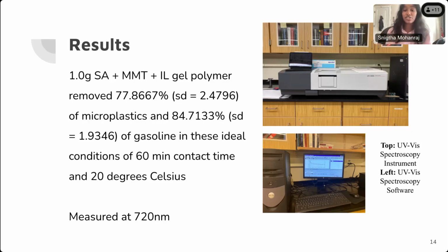And then there was this characteristic peak in a lot of the samples around 720 nanometers. And like I said, I've been working in water contamination for a while, and I've seen that microplastics in oil are very sensitive within the absorbance values in spectroscopy around the same range. And so that's why I focused on just 720 nanometers here.